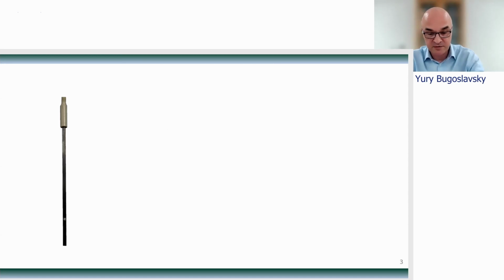The simplicity of the VSM is largely due to the ease of sample preparation. The measurement is contactless, which means there is no need to solder or bond any electrodes to the sample. In fact, all you need to do is just to glue your sample to a light rigid stick. The sample holder shown here is a 10 centimeter long carbon fiber rod, and the sample is a small shiny ball we can just make out near the bottom end of the rod.